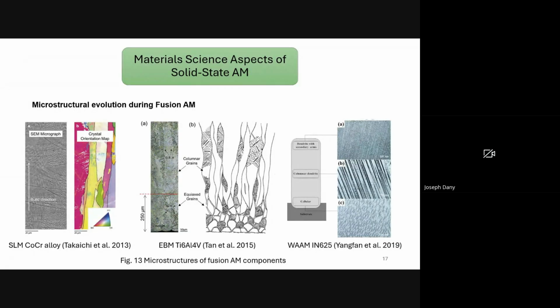Selective laser melting uses a high-power laser to selectively melt layers with rapid localized heating and cooling cycles. The microstructure in SLM parts typically exhibits a very fine cellular and dendritic structure, as we see in figure 13, with strong directional solidification along the build direction. Because cooling rates are extremely high, the microstructure shows very fine primary dendritic arm spacing and fine subgrain cellular structures.